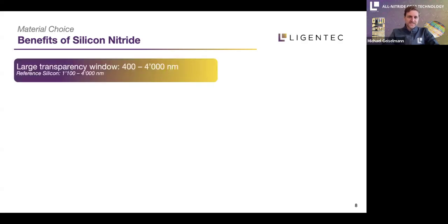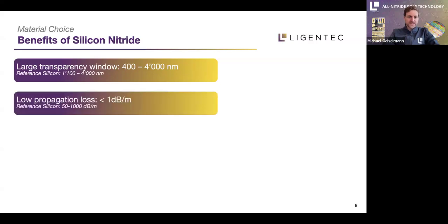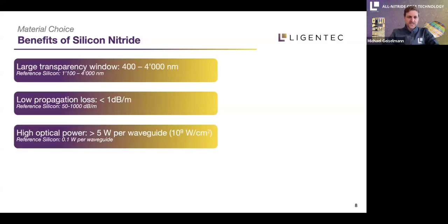So probably for those who don't know yet, I assume that everybody does, but for those who do not yet, the benefit of silicon nitride is a very large transparency window. You see that already from the applications, from 400 nanometers up to the mid-infrared. You can get very low propagation losses in that technology, and you can propagate a lot of optical power through the waveguides. We measured 5 watts in a waveguide, which is like 10 to the 9 watts per square centimeter.